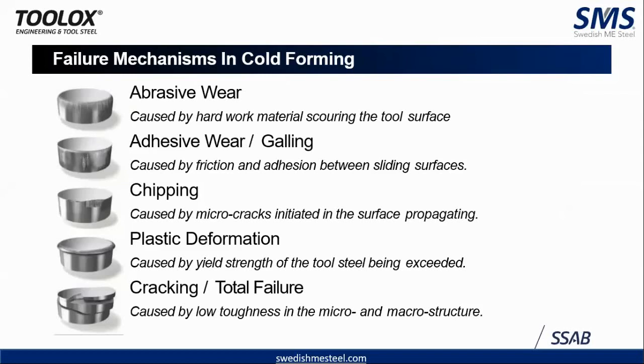When we go ahead with the failure mechanisms in cold forming, these are being listed. Abrasive wear is caused by a hard working material scoring the tool surface. Adhesive wear is caused by friction between sliding surfaces. Chipping, as you all are aware, is caused by micro cracks initiated in the surface and propagating. Plastic deformation is caused by low yield strength, and cracking is caused by low toughness. And how does this material help you out?